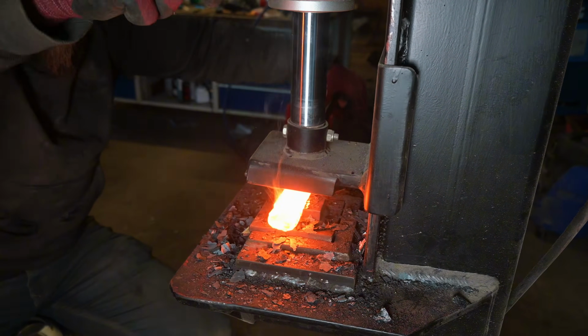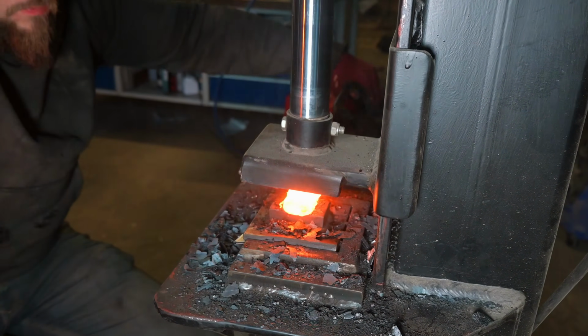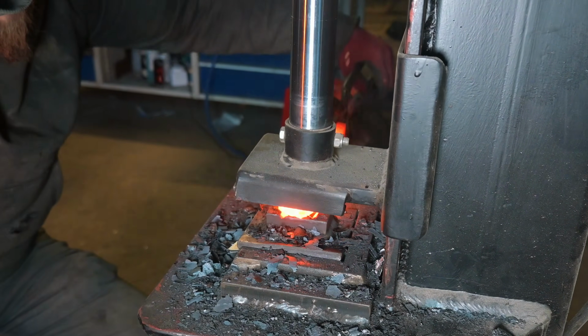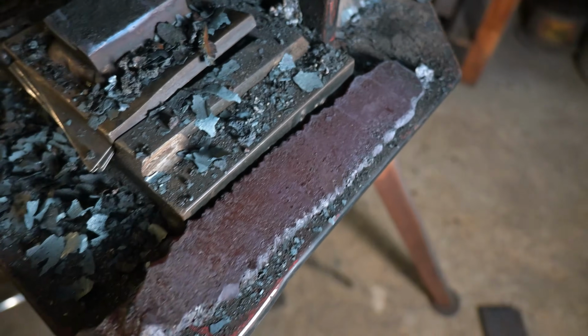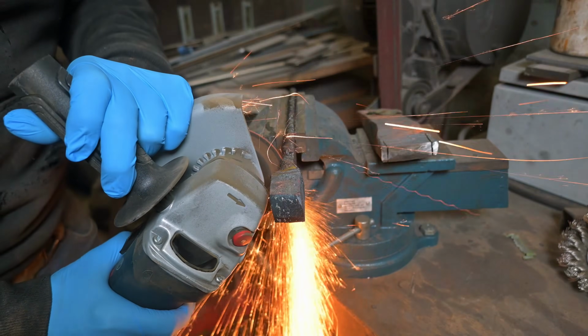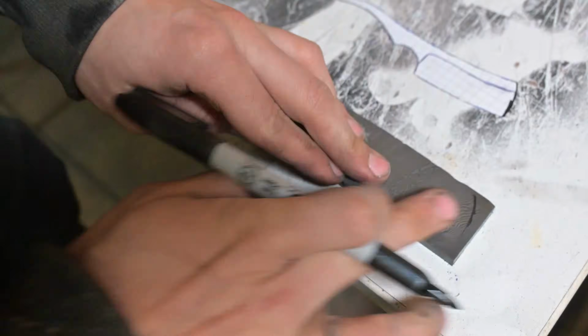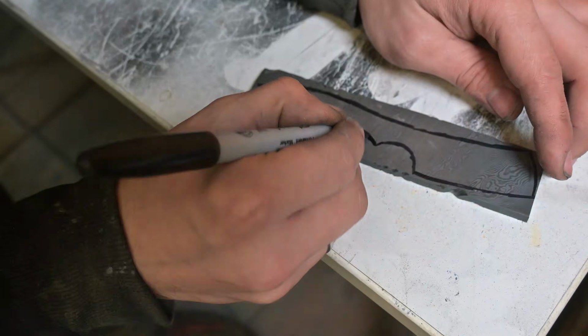After the twisting, I had to forge the steel flat again to get a thickness of material that I can work with. With twisting you lose a lot of material. You have to cut off both ends of the piece because they don't have a really nice twist in them, and you don't want to have that in the end product.